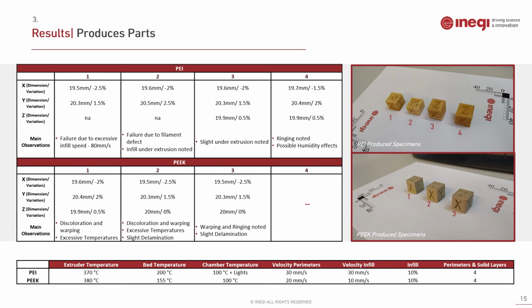The results from all the parts produced are shown in the table. Concerning the PEI produced parts, after 4 trials and some adjustments, we were able to produce a part which we deemed to be in good working condition. The best printing setup experimented is the one described in the table at the bottom, in which we had the extruder temperature at 370 Celsius degrees, the bed temperature at 200 Celsius degrees, the chamber temperature at 100 degrees plus the lighting system, a velocity for both infill and perimeters of 30 mm per second, an infill of 10%, and 4 perimeters as solid layers.